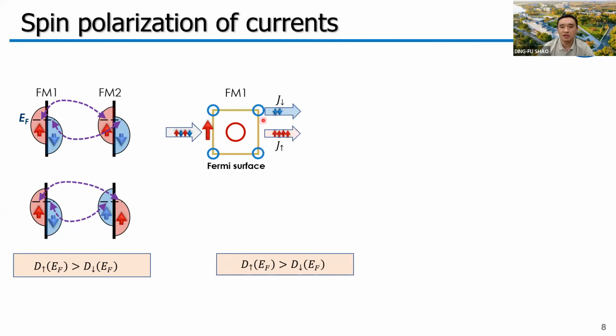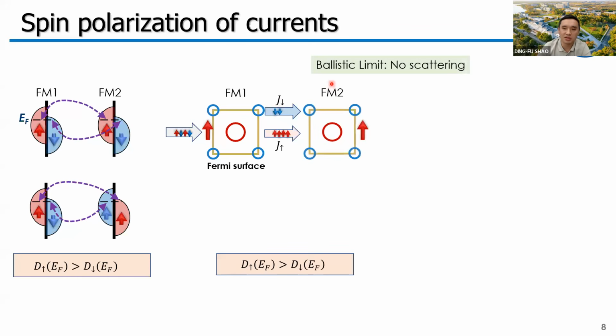And then we consider we have ballistic transport, which means we do not have any scattering. So if we have two identical electrodes using such a ferromagnet, during the tunneling, because we do not have scattering, the tunneling is completely determined by matching of the Fermi surfaces of the two electrodes. So in the parallel state, for the two electrodes, the spins are the same on the Fermi surface.